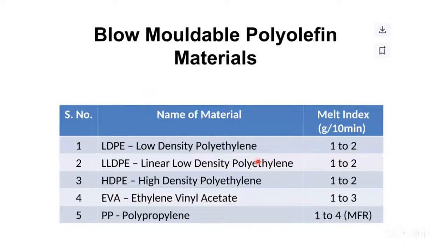See now here, MFI, melt flow index. Remember this thing, it's a very, very important thing. Melt flow index for blow molding requires 1 to 2 only per 10 minutes. See, highly viscous LDPE, then highly viscous LLDPE, 1 to 2 only. HDPE, 1 to 2 only. Therefore, 2 grams per 10 minutes, not more than that. Such a material we are using for blow molding purpose. Remember this thing. Therefore, a higher molecular weight is required. Therefore, you will get a higher melt strength. This indicates a higher melt strength here, friend.